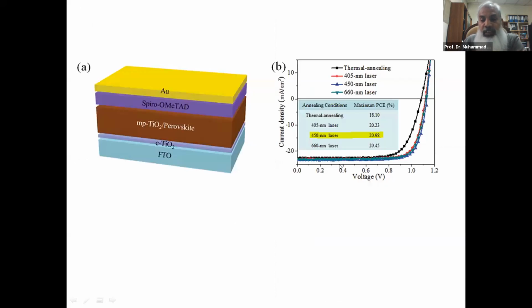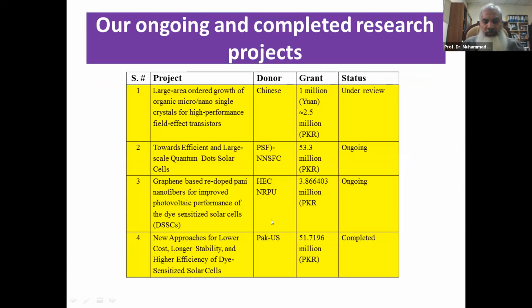And then these films were used in the fabrication of perovskite solar cells. You can see that using a laser diode at 450 nanometer, the results are better than those made using the conventional thermal annealing method.